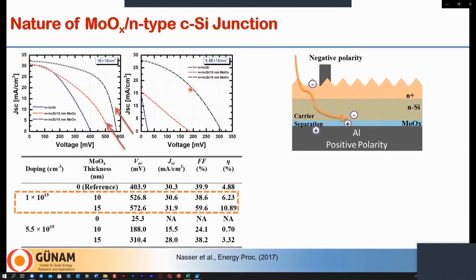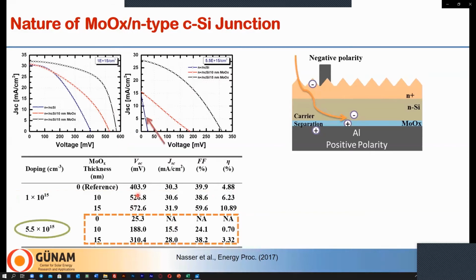Now, placing molybdenum oxide between aluminum and silicon improves the efficiency, and an efficiency of almost 12% is possible with this simple device. For 10 nanometer, we didn't get a good efficiency because 10 nanometer was not enough to fully cover the silicon surface, resulting in some local places where aluminum is touching silicon, as can be seen from the low VOC.